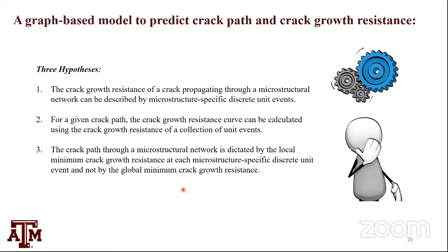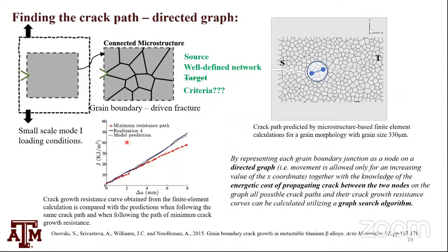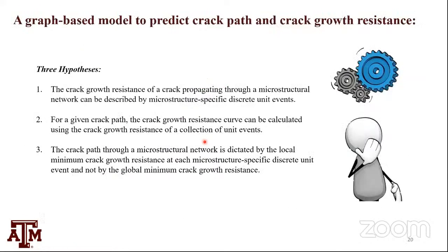The crack growth resistance of a crack propagating through a microstructure network can be described by microstructure-specific discrete units. How and why? Simply because if I take the path that the finite element gave me, and if I know the energetic cost, then I can just sum each part and get the curve. If I do that, this is the blue line. It matches. So if I know the unit cost of propagating each step and I know the path, then I know the curve. I don't know the unit cost yet, and I don't know what gives me the path yet. But if I know those, I can find out.